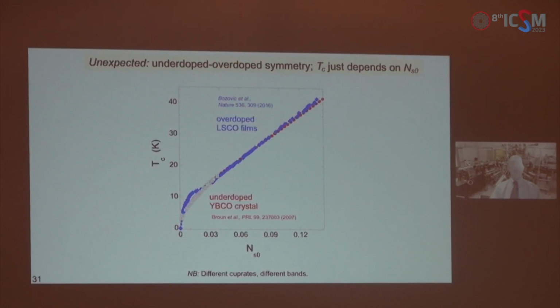I have mentioned already the strain dependence of Tc on the zero temperature superfluid density, which is essentially linear but with finite offset, except very close to the origin where it turns to a square root dependence, as one would expect from quantum critical phase fluctuations. Almost identical dependence was seen in a different cuprate by a different group, using a different technique. Moreover, it was on the heavily underdoped side, while our LSCO is on the overdoped side. So the point is that it appears that, as Jan Zaanen would say, there is some very powerful and simple principle at play.